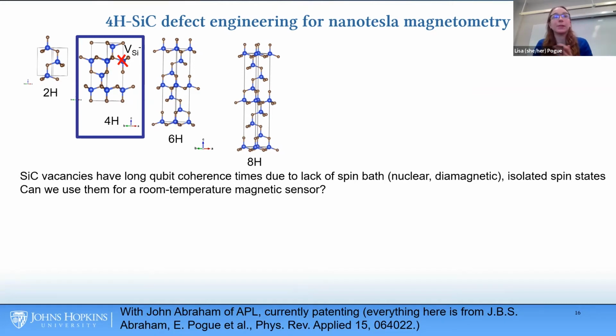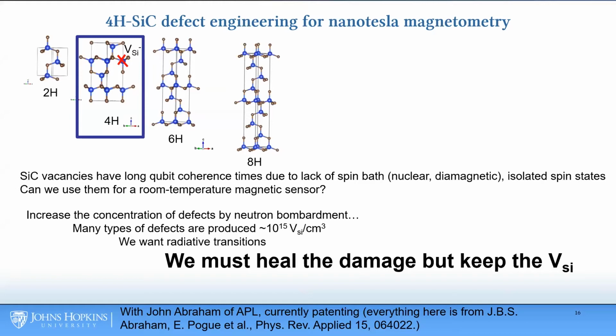Yeah, so silicon carbide vacancies. The question was whether or not we could use this as a magnetic sensor and whether we could engineer the defects, the vacancies, and other defects produced when introducing the defects into these materials. And if we could get it so that we could get strong enough signals out. Could this magnetic sensor work at room temperature? We found that yes, we could.